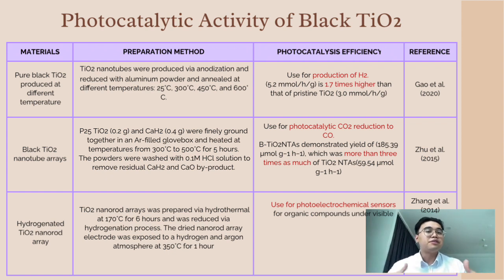Now, we will review the photocatalytic activity of different synthesis methods of black TiO2. The first synthesis method, which is aluminum reduction, the material produced is pure black TiO2 produced at different temperatures. Here we can see that it is used for production of hydrogen gas. It is 1.7 times higher than the hydrogen produced in pristine TiO2.